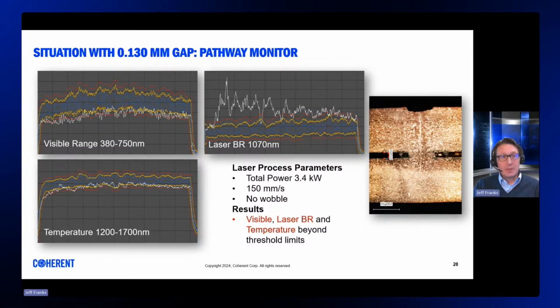As we introduce a gap, in this case of 0.13 millimeters, we can immediately see the process or visible signals dropping low, whilst the back reflected laser light generates a clear error condition breach at that wavelength. As less power gets coupled into the weld, the temperature wavelength signals drop below their lower warning threshold. Whilst the weld may still produce a reasonable connection, the performance would certainly be below that of the zero gap condition.